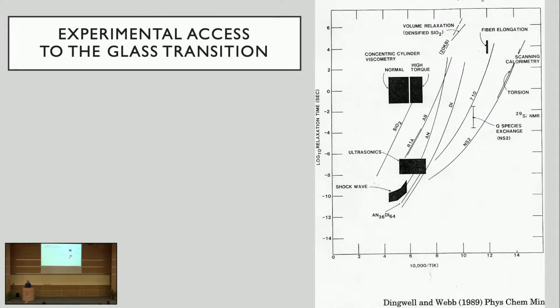So when we do experiments to get close to the glass transition, we can plot the relaxation time versus reciprocal temperature of samples. So here we have SiO2, here we have a sodium alumina silicate, here we have a calcium magnesium silicate. They all have their own individual compositionally variable values of relaxation time versus reciprocal temperature. And every time we try to measure their properties, our experiments have a value of temperature where we're doing the experiments, but they also have a value of observational time. And sometimes this is not appreciated well enough in the literature, because if you have the goal of understanding the thermodynamic equilibrium properties of these liquids, you must be to the left of these curves. You must be in the relaxed state, and that means you have to choose an experiment which takes a long enough time of observation such that the data you receive are in the relaxed state. Only then can I go into the Earth and try to understand what the relaxed state is in the interior.